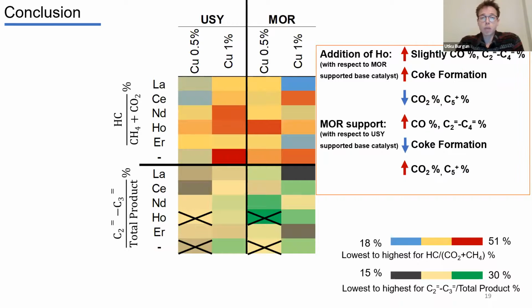So as a conclusion, we have synthesized 24 catalysts and tested them at atmospheric pressure using a high throughput test system, and 4 catalysts were selected to be tested in a pressurized test system. The addition of holmium with respect to the mordenite supported base catalyst slightly increased carbon monoxide conversion and C2-C4 selectivity, increased coke formation, and decreased carbon dioxide and C5+ selectivity. And using mordenite support with respect to the ultra-stable Y supported base catalyst increased carbon monoxide conversion, C2-C4 selectivity, decreased coke formation, and increased carbon dioxide selectivity and C5+ selectivity.